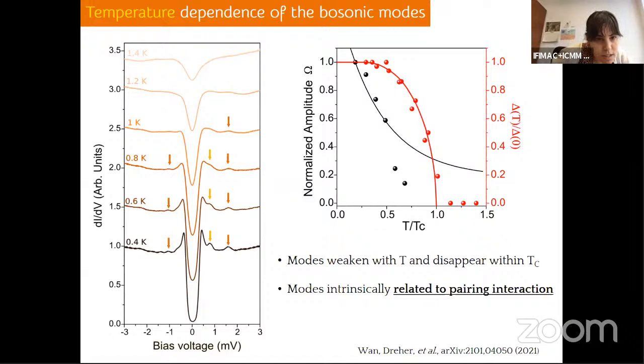Or at least it is at the same position. It doesn't change the position. You're saying that it remains constant. With the magnetic field, the size of the gap diminishes, so basically it becomes smaller. Yes. Well, I'm saying that the energy of the bosonic mode doesn't seem to increase when you decrease the size of the superconducting gap with temperature.